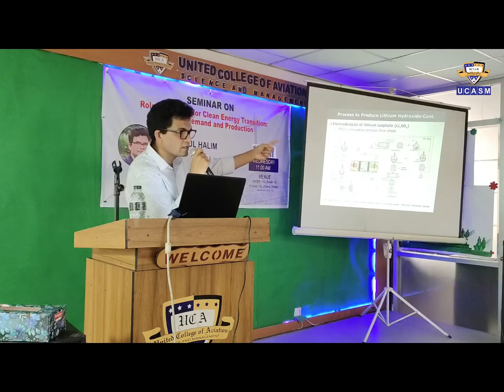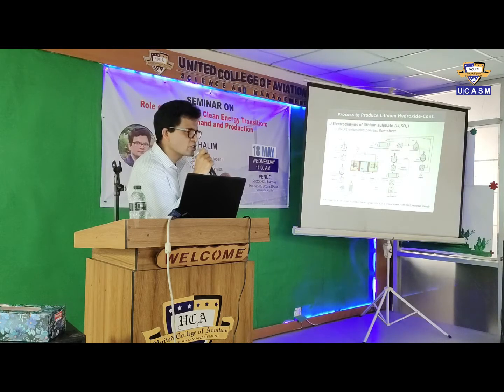And after that, the lithium hydroxide concentration is a key parameter. In these cases, we can increase the concentration as much as we can. That reduces the evaporation cost, the energy cost to produce the lithium hydroxide, as the lithium hydroxide is a solid. But it is not 100% recovery. None of the flow sheets give you 100% recovery. There will be 10, 15, 20% in a liquid form. That needs to be counted to make this flow sheet more economically viable.